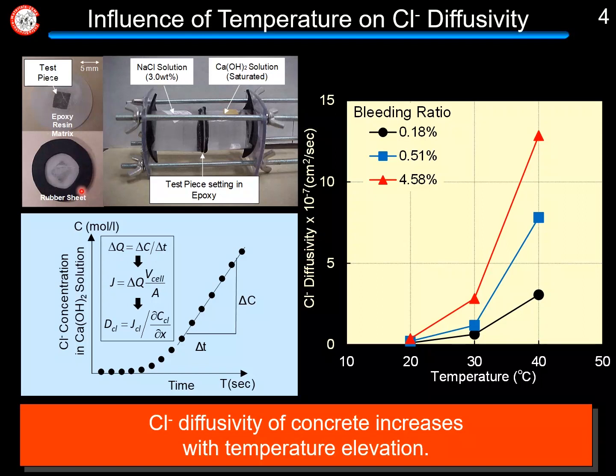The test piece, formed with epoxy resin, was set in the diffusion cell as shown here, and the two cells were filled with 3% sodium chloride and saturated calcium hydroxide respectively. This diffusion cell was exposed to an air-controlled chamber set at 20, 30 and 40 degrees centigrade, and the chloride ion concentration in the saturated calcium hydroxide was measured every day. Then the chloride ion diffusivity was calculated by Fick's law.